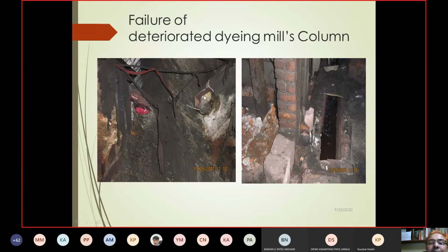This is the pipe, and these are the chemicals. The pH is less than 7. So the pH is 4 or 5 in a dyeing mill. This chemical wastewater is coming from this top pipe, and it should go into this pipe. But this pipe is broken. No one cares to repair this pipe, and they are sprinkling all this low pH water on this column, and that's why the result is that the column is in a compromising condition.